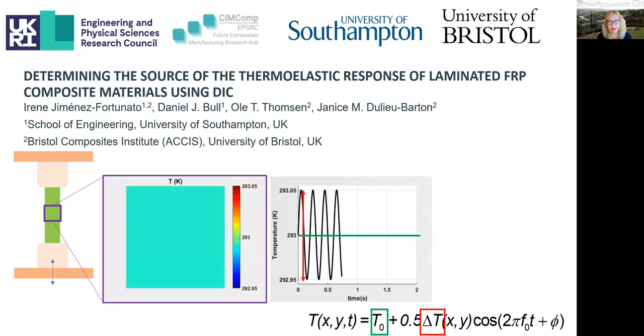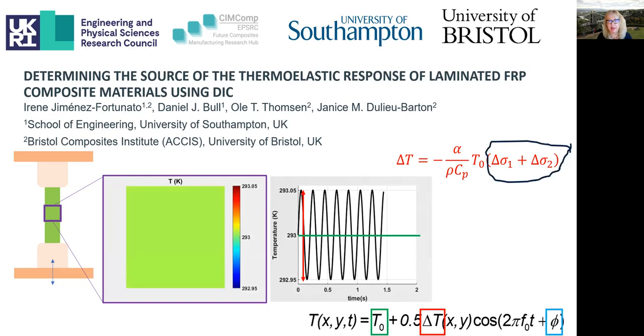Delta T, the range of the temperature change and also phi, the phase of the temperature change. In the context of this presentation, the important quantity here is delta T, which is the thermoelastic response and this is directly related to the sum of the principal stresses.